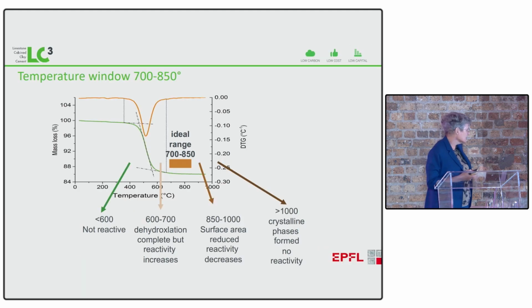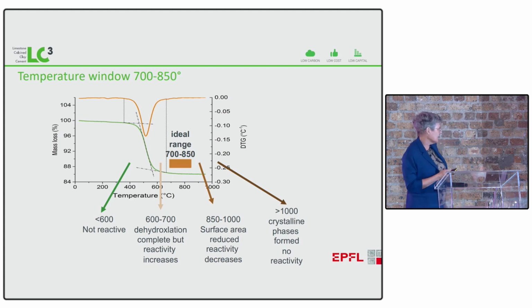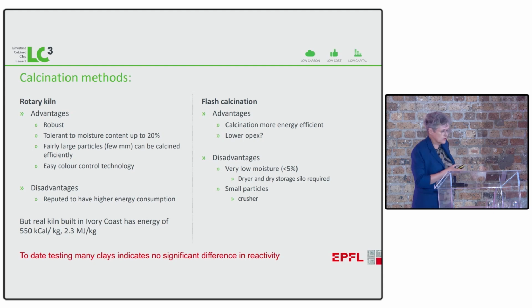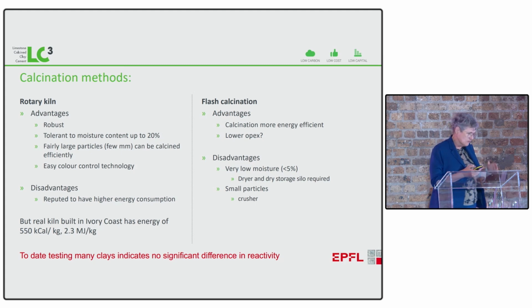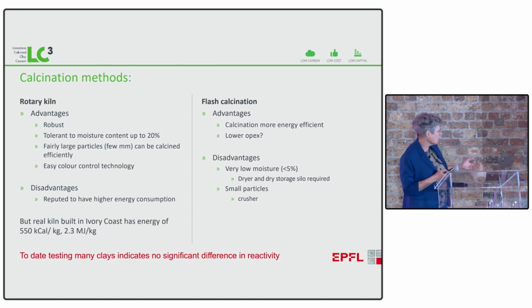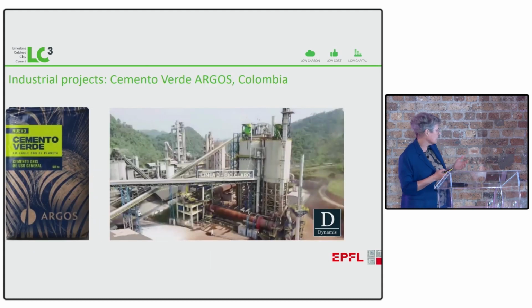The clay you calcine with existing technology, you want to be in this temperature window, 700 to 850, and you can do this either with rotary kiln or with flash calcination. There's not really much difference in the reactivity you produce. The rotary kiln tends to be more robust. You can deal with higher moisture contents.